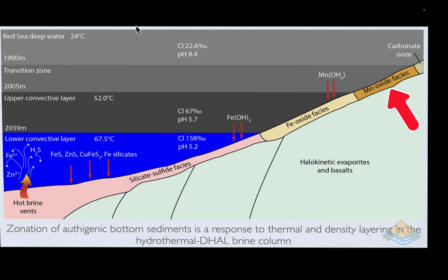We have the manganese oxide facies. Then as we go into the upper convective layer, it's equivalent to the conditions that favour the precipitation of iron oxides. And then in the lower convective layer, where we get the silicates and the sulphides accumulating, we have our hottest brine temperatures and also our hottest salinities, as we can see in the chlorinity profiles, and also our most acidic conditions in terms of pH, going from a pH of 8.4 in the deep normal bottom waters of the Red Sea through to a pH of 5.2 in that lower convective sulphide-rich layer.